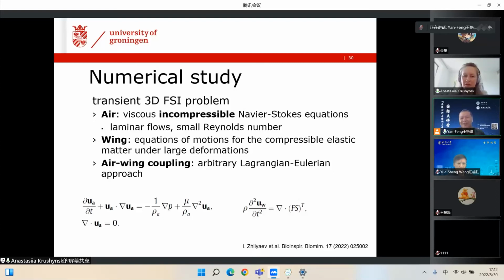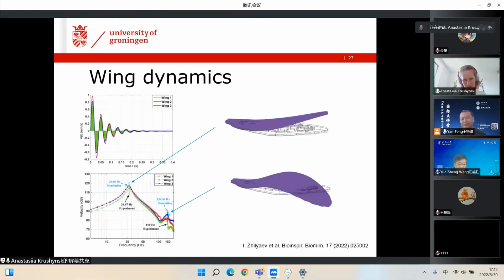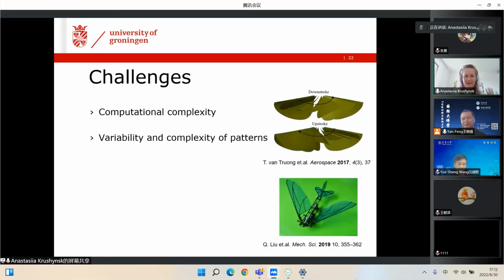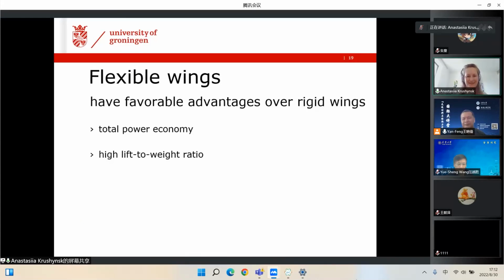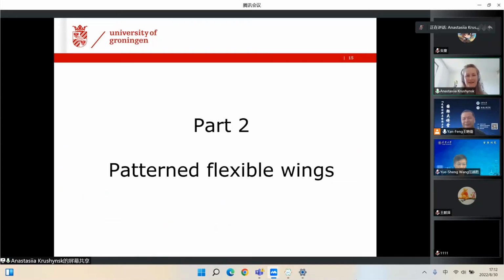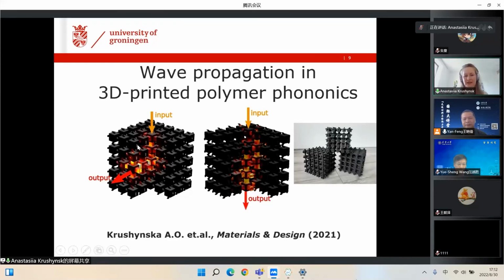Yeah. Okay. Because in modeling phononic structures, we really have very complex problems. We not only have material viscosity, but we also have variations in the amount of material, right? So we can have, for example, in that example which I showed, just a second. I cannot go out of full screen regime, but it will not take too much time. Like in these structures, we have variations between bulky parts and slender parts. This is also very difficult to capture when we consider viscoelastic moduli.